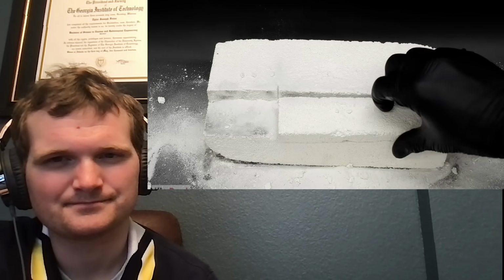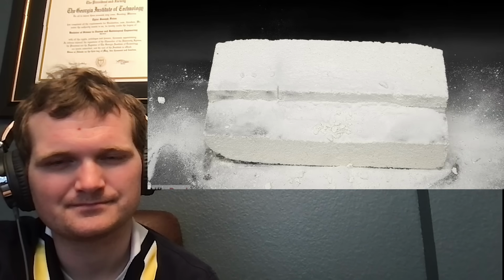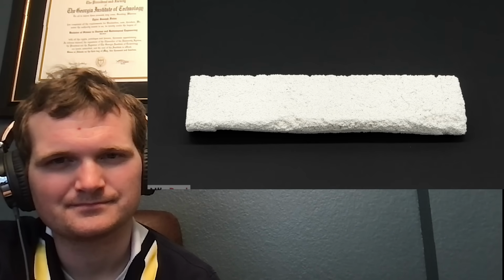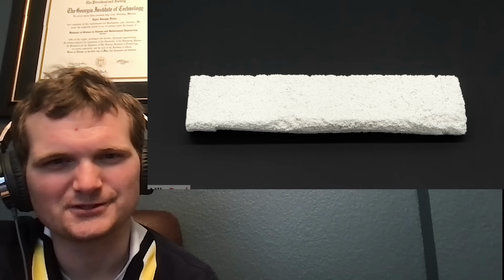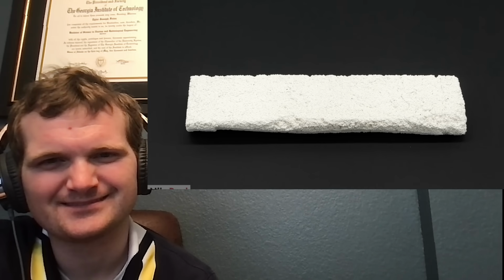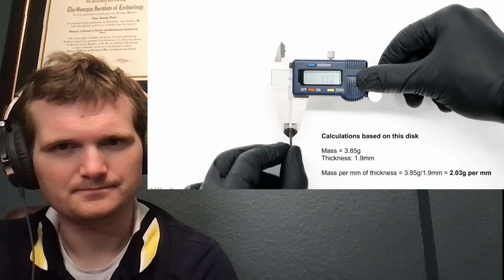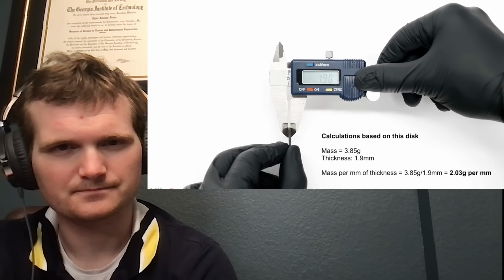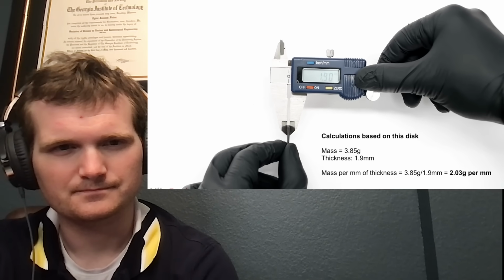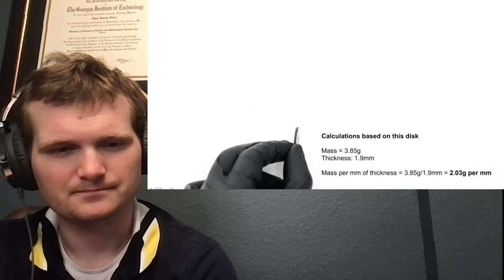I sized it to be the biggest thing that I could fit in the furnace, and it looked like it could hold 5 pellets. So, that was how many I was going to make. Now, in terms of pellet thickness, I had to decide how big I wanted them to be. For the first one, I just crushed what I had, and it ended up being about 1.9 millimeters. But now, knowing that it was 1.9 millimeters and that it weighed 3.85 grams, I could calculate the amount that I needed for any thickness.